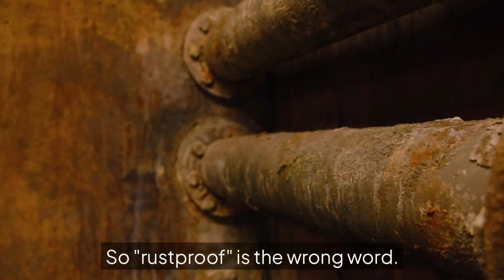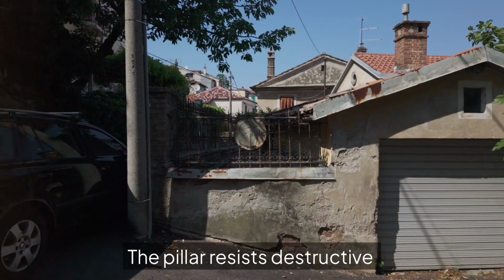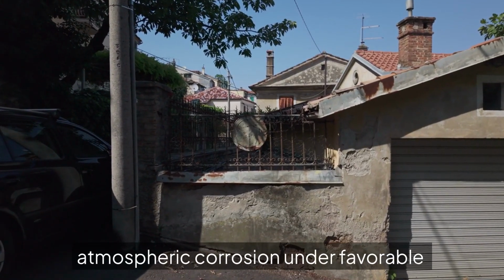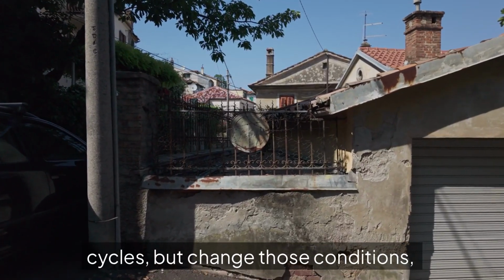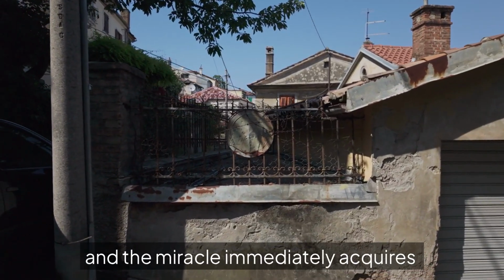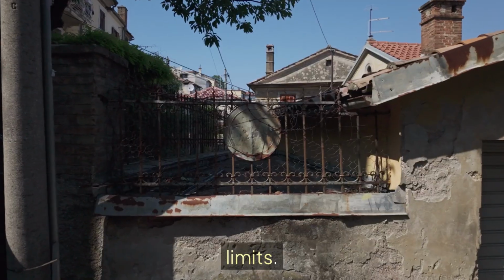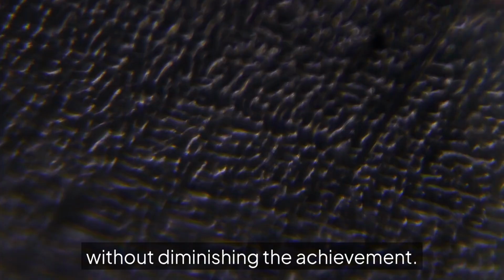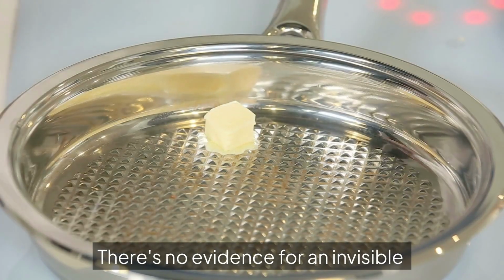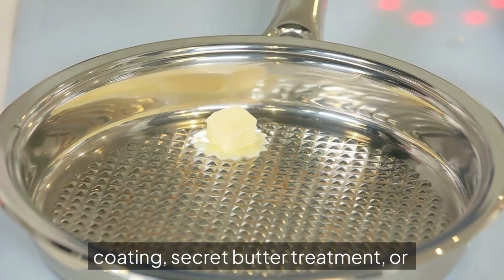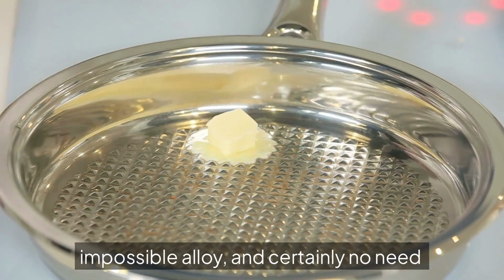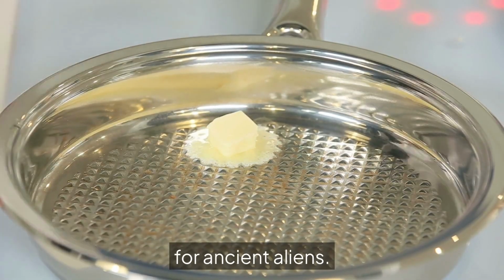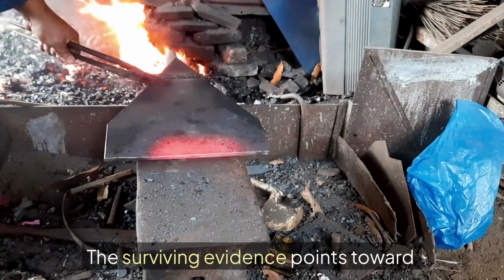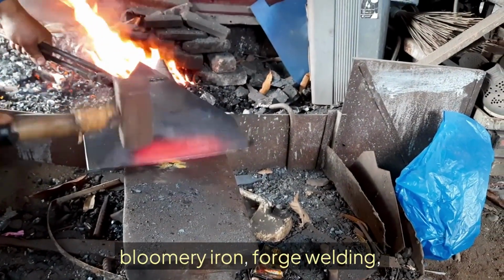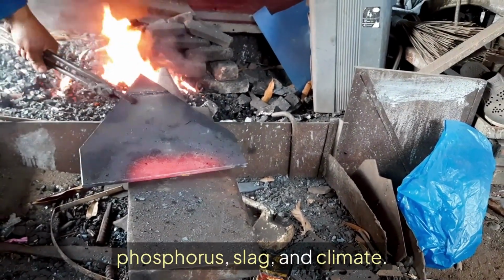So rust-proof is the wrong word. The pillar resists destructive atmospheric corrosion under favorable cycles, but change those conditions, and the miracle immediately acquires limits. Those limits dismantle the mythology without diminishing the achievement. There's no evidence for an invisible coating, secret butter treatment, or impossible alloy, and certainly no need for ancient aliens. The surviving evidence points toward bloomery iron, forge welding, phosphorus, slag, and climate.